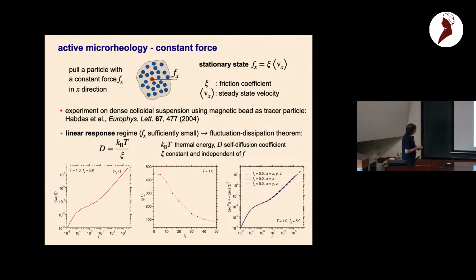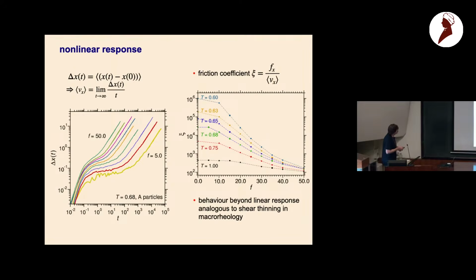Now, interesting now is this nonlinear response regime. This shows different displacements as a function of time for temperature 0.68, and we vary the force from 5 to 50 here. The corresponding, in the stationary regime at long times, steady state velocity, and from this the friction coefficient, the corresponding curve as a function of force is shown here.